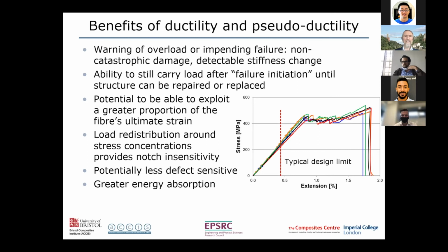So design strains are typically quite low because people are worried about damage and about catastrophic failure. To avoid these sorts of problems, design strains are very low, well below what the composite will take. And our plan with this is that you can actually use a bit more, because so long as you keep below that pseudo-ductile limit, then the specimen remains intact, is not damaged, and this has many benefits. For example, with the load distribution around the stress concentrations, provides notch insensitivity. And this should also make the materials less sensitive to defects and enable large amount of energy to be absorbed.